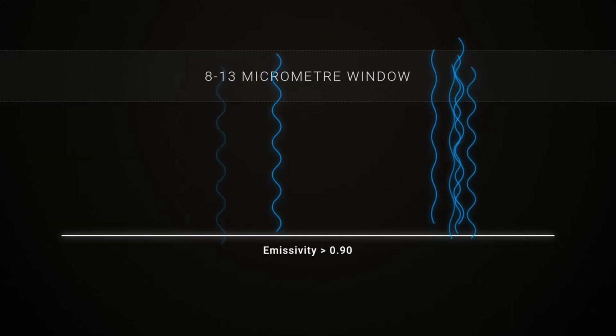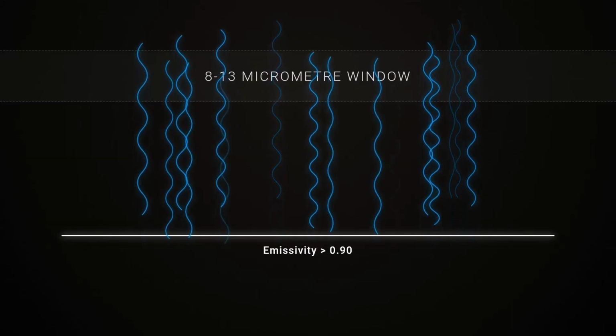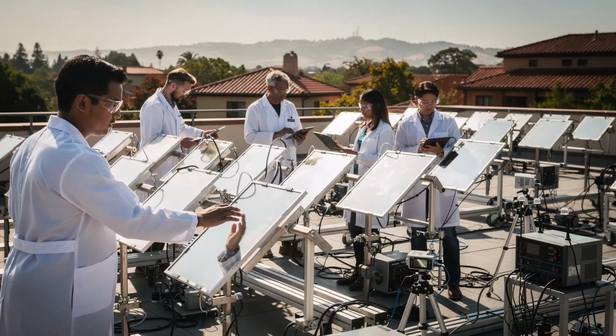How close to a perfect emitter it behaves in the relevant wavelength band. A surface with emissivity above 0.90 in the 8 to 13 micrometer band emits heat through the atmospheric window at a rate that, under clear sky conditions, exceeds the rate at which it absorbs solar radiation. Surface temperature drops below air temperature. This is not a theoretical prediction. It is a measured physical result.